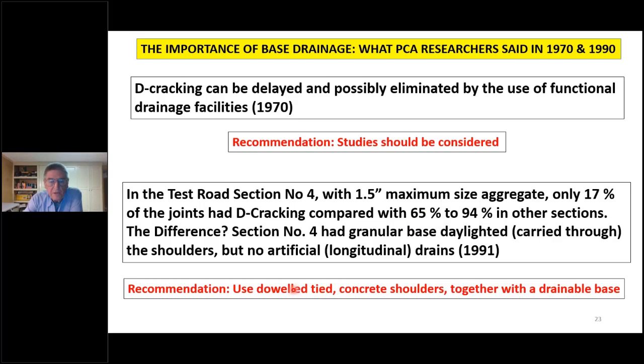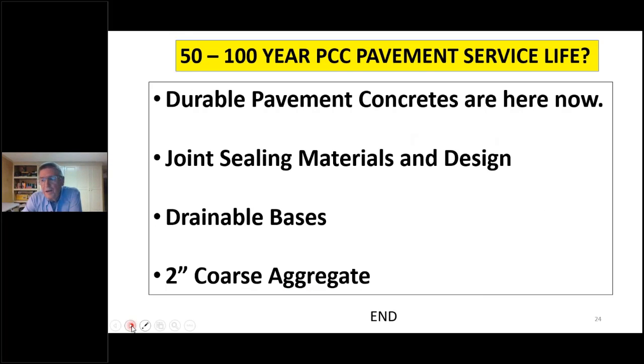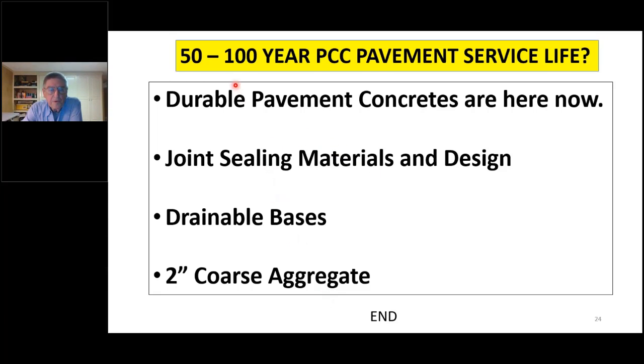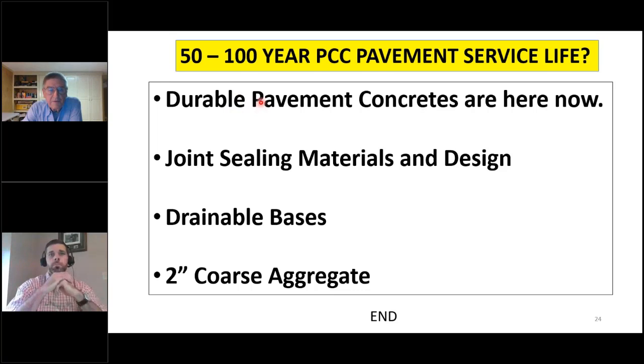They recommended using dowel-tied concrete shoulders together with a drainable base. So again, recognizing the root cause of the problem as being the concrete in a saturated condition, keep the water out. So I think it's not illogical to think that we can do 50 to 100 year PCC pavements in Ohio. We know we can produce durable concrete pavements themselves, even good old Class C made right, particularly with fly ash these days. Maybe that should be mandated to keep the permeability down.